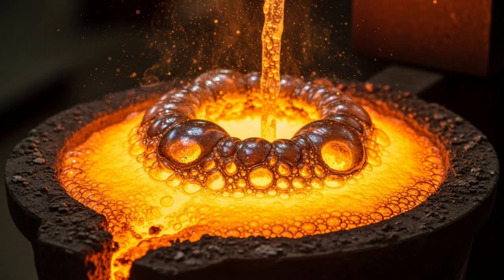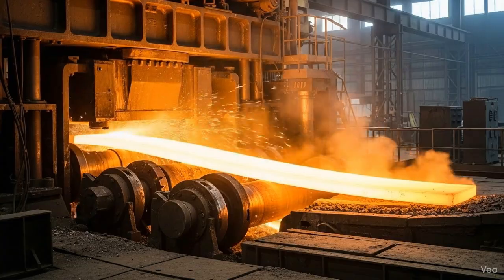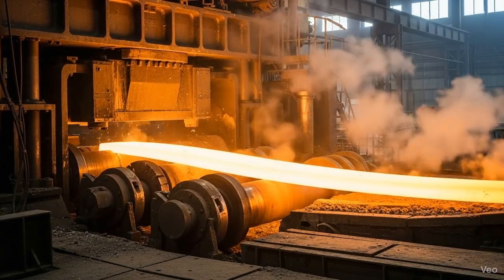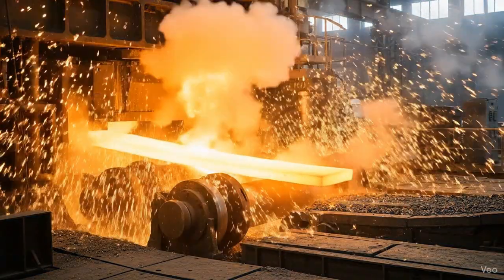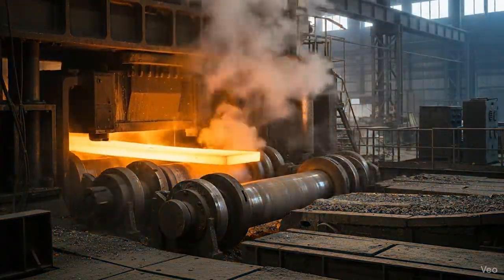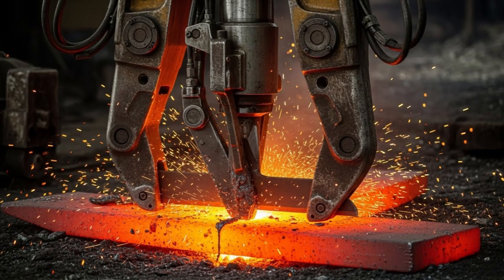Continuous casting. With the liquid part finished, it's time to solidify the metal. The dominant method in the world is continuous casting. The steel flows through a water-cooled copper mold, forming a solid outer shell shortly after leaving the nozzle. As it descends through rollers, the piece takes the shape of a slab, square billet, or rectangular block. Hydraulic shears cut precise lengths while the interior is still orange-red. It's a hypnotizing spectacle. Incandescent blocks of dozens of tons sliding, as if they were bars of soap, emitting white smoke from steam.